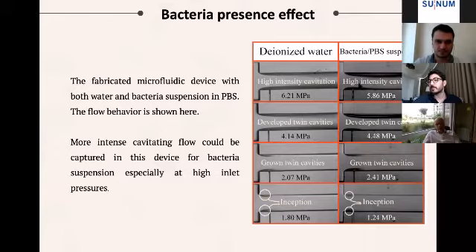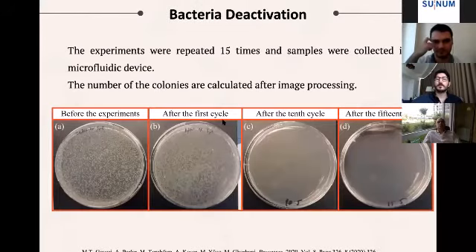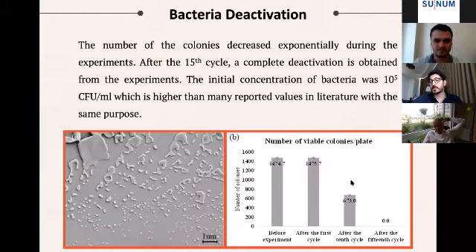So these two patterns were visualized at lower upstream pressure compared to the deionized water. We did the experiments at different cycles. After the first round, we didn't see any significant decrease in the population of the bacteria. However, after 15 cycles, we found that there is no bacteria in our solution. After the post-processing, we found this reduction in the number of viable colonies, which is very, very important.